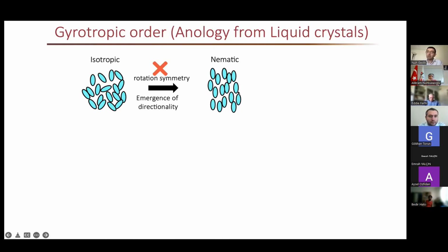Now, it turns out that in quantum materials, there's the analog of this. We have materials in which, at high temperature, the material is completely symmetric. But then if you cool it down, electrons suddenly decide that they prefer one direction over the other. They go through this nematic transition where the lattice could be fourfold symmetric, but when you cool below a certain transition, electronic wave functions are only twofold symmetric. So they prefer one axis over the other axis. This is called nematic. So there are examples of nematic phases in quantum materials.